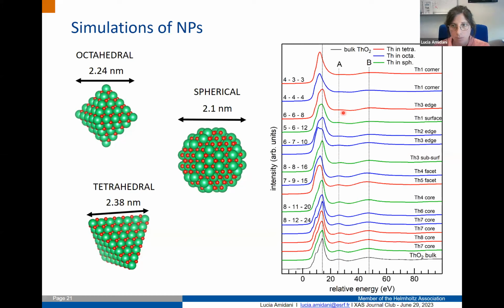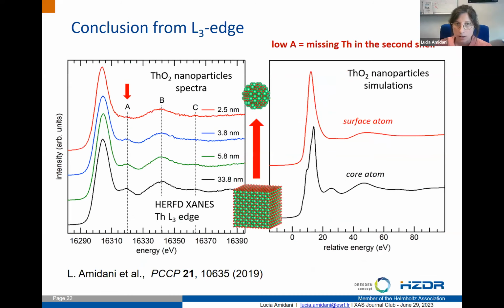In particular, the A structure goes lower, and you can see that the only cases where we really don't have it are in the cases of corner atoms. So this first investigation concluded that we were not able, by taking the full nanoparticle, to reproduce completely the spectrum if we average all the contributions from core atoms and surface atoms.